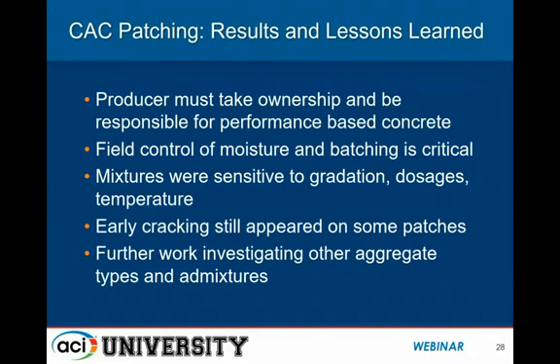The mixtures, as I said, there was some sensitivity. The early strength was somewhat sensitive to the presence of moisture in the aggregate, and also the gradation and the admixture dosages. So there are things that need to be watched for in this material, and as we continue to do further work investigating it in the field, I think that in particular in the Illinois Tollway system, we're going to continue to see improvements there.